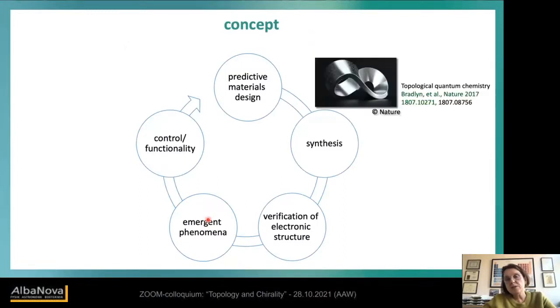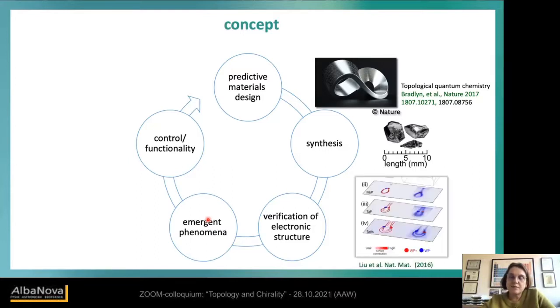So we do first some theory, or we look for a theoretical prediction from some theoretician, or we are involved in some theoretical prediction like high throughput. So we then make the synthesis of the crystals, and we wait that Igor maybe makes a nice prediction, or we are now working with his friend Maxim. He came up also with many predictions, so we make the corresponding single crystal. So we try to verify the electronic structure, and very often this is by photoemission, because angle-resolved photoemission allows us really to compare the theoretical band structure, the electronic structure, so really see whether we have this band inversion. Here we have a semi-metal, which I will explain in a minute.